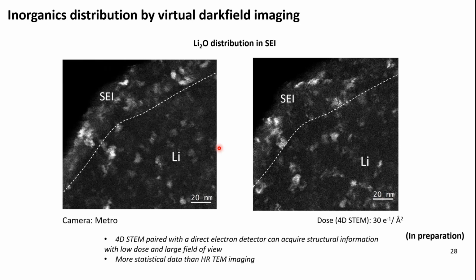If you have a direct electron detector, you can acquire structure information with those rates. And unlike high resolution imaging, you don't have to damage your samples while locating and navigating your samples. At low magnification, you can draw a rectangular spot where the beam is rested over your region of interest, and you can acquire 4D STEM data with the large field of view.